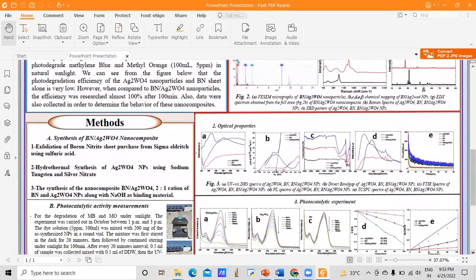So here is our synthesis method. First, a boron nitride sheet purchased from Sigma Aldrich was exfoliated using sulfuric acid. Then hydrothermal synthesis of Ag2WO4 nanoparticles using sodium tungstate and silver nitrate. Then the nanocomposite was made in a ratio of 2:1, using BN and Ag2WO4 nanoparticles along with NaOH as binding material.